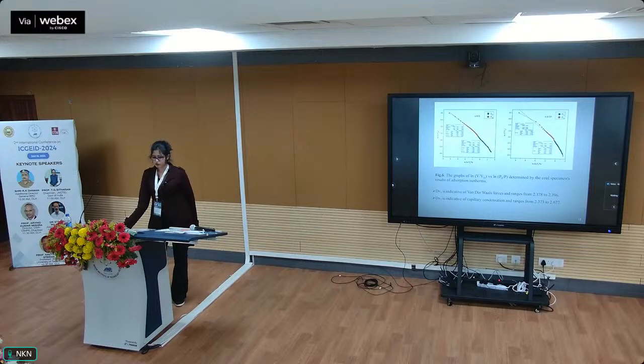These two fractal curves indicate the adsorption stages, which are mainly the van der Waals region and the capillary condensation region. And these two correspond with the relative pressure range of 0 to 0.45 and 0.45 to 0.99. D1 that is derived from the lower relative pressure range varies from 2.378 to 2.396, and D2 that is derived from the high relative pressure range varies from 2.73 to 2.677.